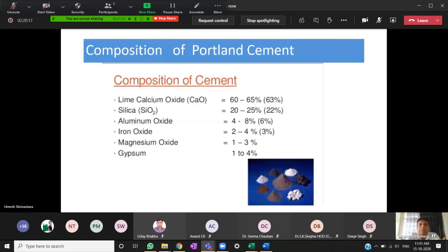The lime deposits will have different concentrations of lime, different concentrations of silica and alumina, while our plant needs a certain band, so you require all the time corrections of lime, silica and alumina. These are three very important things: lime, silica and alumina. Whosoever is in the cement industry knows that LSF, the lime saturation factor, is very important for process stability, and in order to maintain the quality of the final product, they have to maintain the LSF.